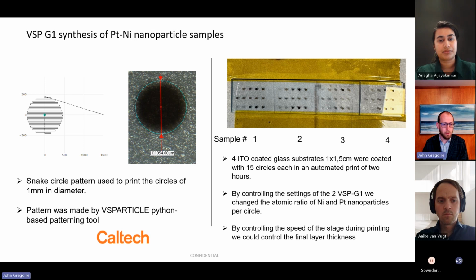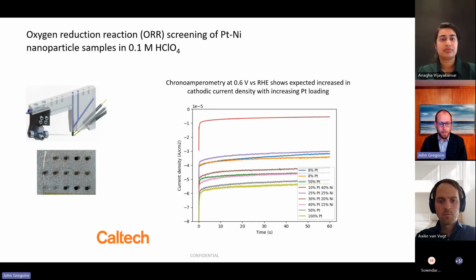The rastering speed here can control the nanoparticle loading, or the metal loading, of our sample. We're then making an array of dots that are very intentionally analogous to that inkjet printing array so that we can use the same scanning droplet cell to measure the properties of these different dots. The first thing we looked at was, we're also here going to look for oxygen reduction chemistry. The results I showed you previously from inkjet printing were oxygen evolution, but for starting with a binary metal nanoparticle system, we thought it would be a better validation study to look at acidic oxygen reduction.